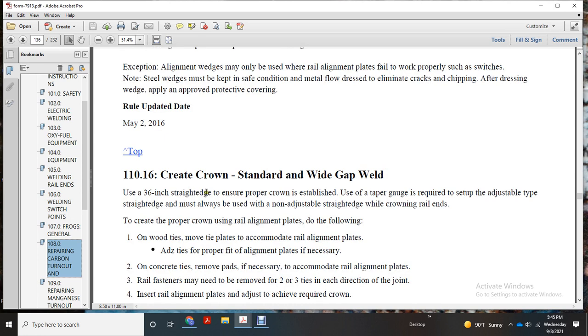A 36 inch straight edge is used to ensure a proper crown is established, with the taper gauge required for the setup. The adjustable type of straight edge must always be used, with the non-adjustable straight edge for the crown of the rail ends. To create a proper crown, use the rail alignment plates, for the following reasons. On wooden ties, move the tie plate to accommodate rail alignment plates. Add ties for the proper fit with alignment plates if necessary. On concrete ties, remove the pads if necessary to accommodate rail alignment plates. Rail fasteners may need to be removed from 2 or 3 ties in each direction of the joint.